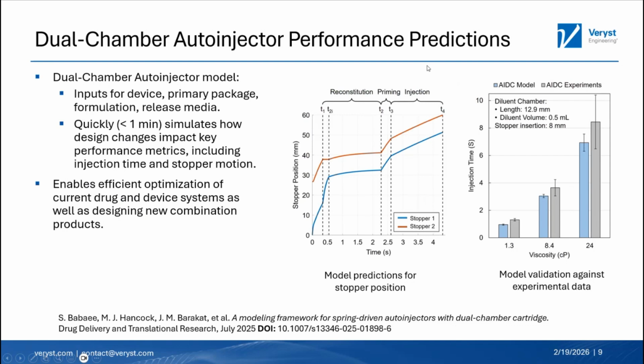So the dual chamber autoinjector model that we developed has inputs related to the device, to the primary package, the formulation, and the release medium. Since the model is reduced order, this is just solving a differential equation in time. It solves within about a minute to simulate how the design changes impact key performance metrics. And these performance metrics would include things like injection time and stopper motion. The predicted stopper trajectories are shown in the left plot through the various stages of operation. Notice the rapid initial motion, and then later on, there's an equilibrium just prior to seal puncture, priming, and injection.